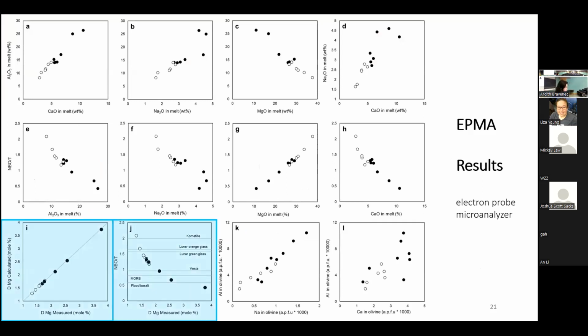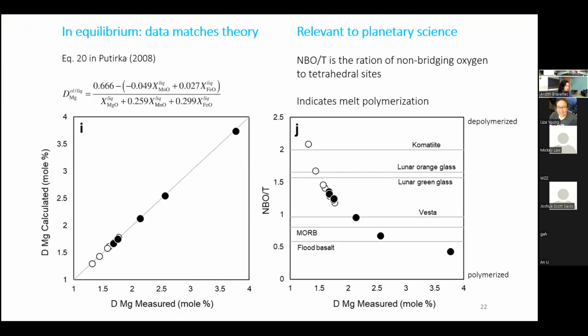And that's going to be that these samples are in equilibrium, which we can test through the partitioning of magnesium between the crystal and the melt. And this is well characterized in experimental petrology as a test for equilibrium of crystals. And sure enough, my data seems to match theory perfectly. So there's nothing too strange going on in terms of equilibrium.